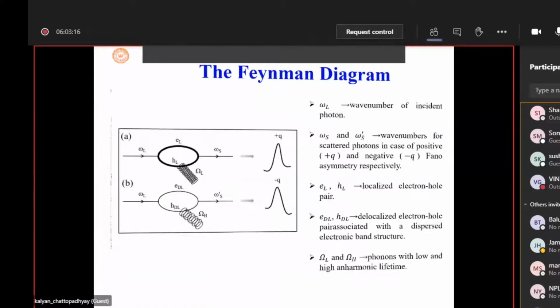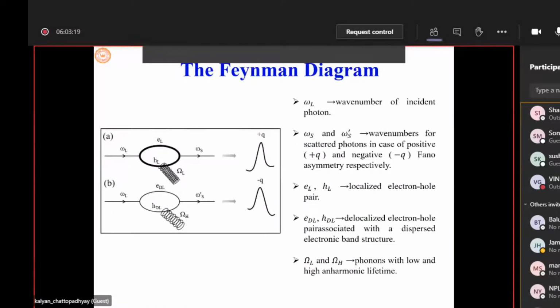So the take-home message is represented by this Feynman diagram, so that without doing any rigorous calculation, if you look at this system, say if you have a localized electron hole system, okay, localized plasma, so L represents localized, that means not dispersed. And then if this is the incident frequency of the incident photon, the Raman probe, and this is the scattered frequency. Now, when it is localized, you have low lifetime of the phonon and you get positive Q. On the other hand, when you have a dispersed electron hole system, you have high lifetime of the phonon, you get negative Q.